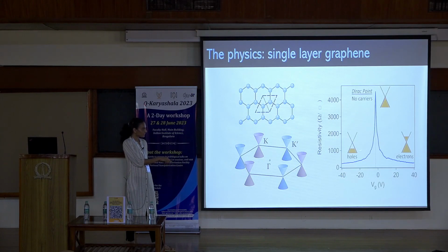So if you apply a negative gate voltage, you have depopulated the valence band, which means that you have populated it with holes. Okay, so you can go from holes to electrons, and then between that you access this Dirac point, or the point where it is just crossing each other. So at that point there are no carriers. So that's why one way to understand this large peak is that there are no carriers here. Here you have electrons, here you have holes. In both cases the resistivity comes down.